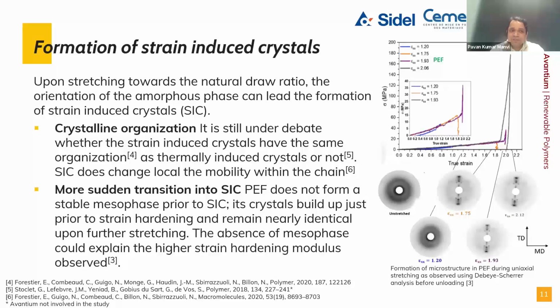So it is not yet fully concluded. There are still some debates ongoing about what the exact differentiation is between the thermally induced crystals and the strain induced crystals. But it is very much clear that PEF does not make any mesophase. Mesophase means nucleation induced by the thermal crystallization, and then continuous crystallization takes place.